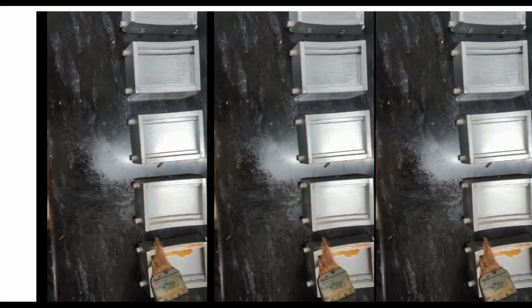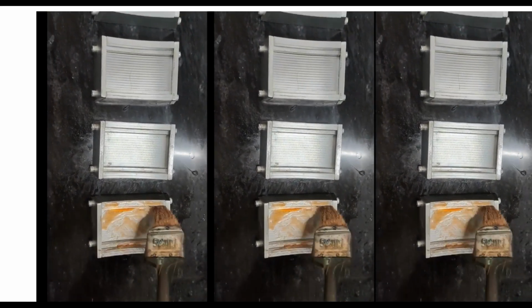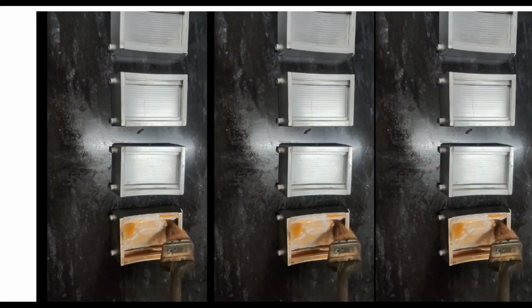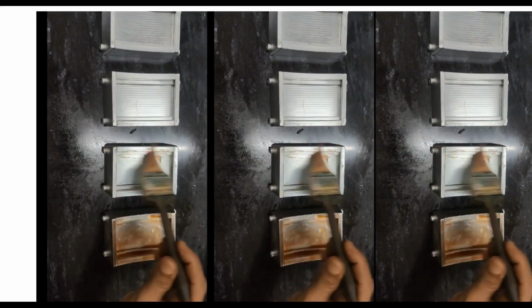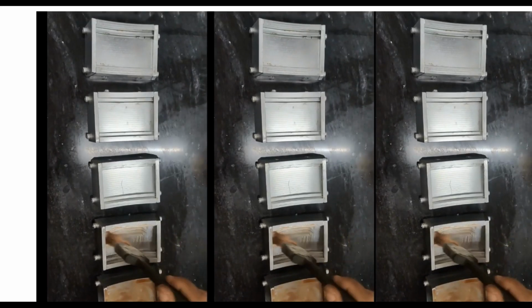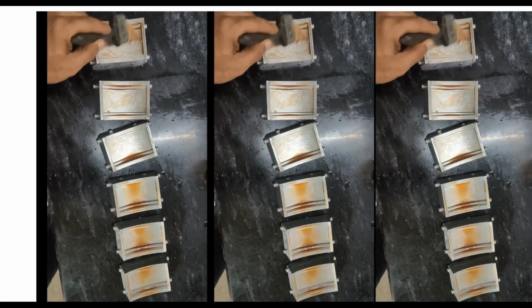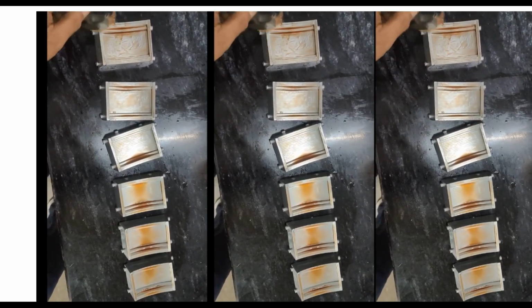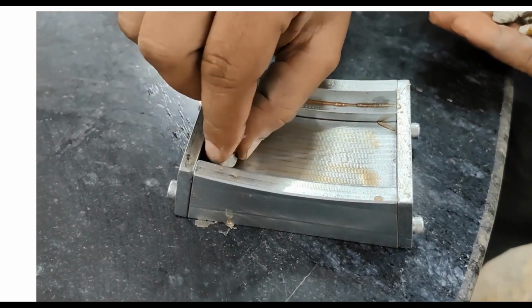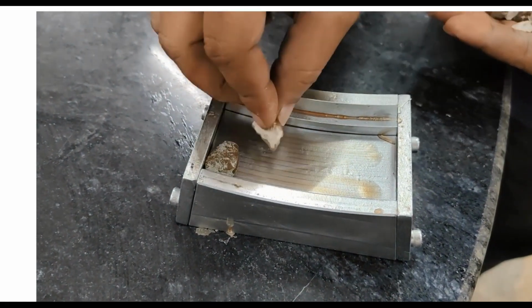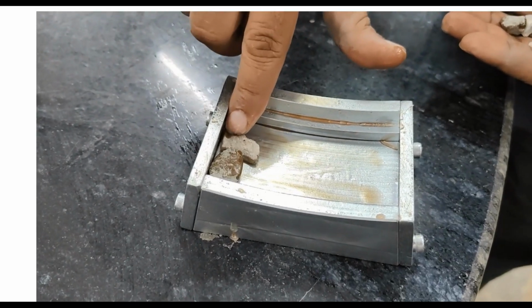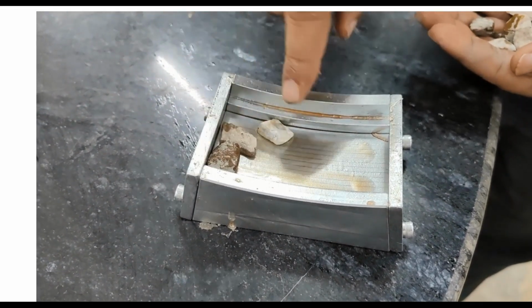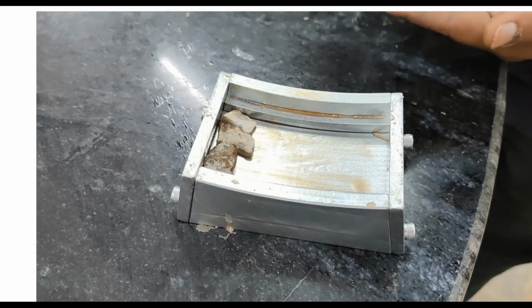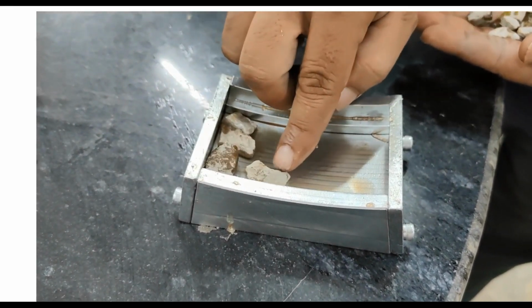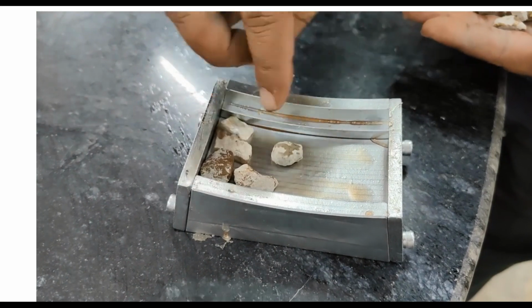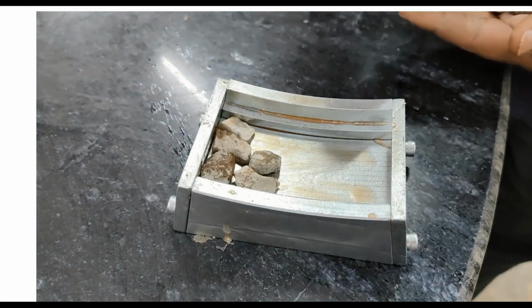Take the mold and oil its surface lightly. This oil can be any mobile oil, and once you oil the surface of all molds, then place the aggregates in the mold one by one as closely as possible in a single layer. The flat surface of the aggregate should be down to cover the bottom surface of the mold.